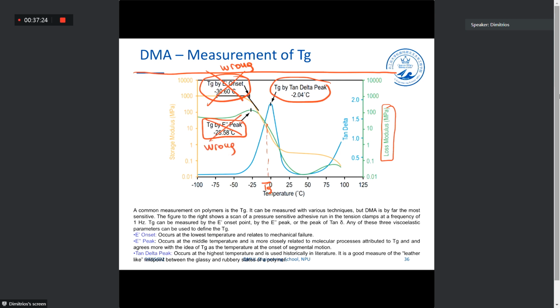And you can see how big a difference there is between the peak of the tan delta or the middle of the storage modulus versus temperature graph, where it shows a big downshift, a big slope. In this case, we have a -2 Celsius degrees glass transition, while the other two methods give us a glass transition of -30, which is wrong. -28 and -30. So anytime someone asks you to identify glass transition from a storage modulus or the tan delta or a DMA measurement in general, you use these two parameters that we discussed. Either the middle of this downshift, this yellow line, sorry, or the peak of the tan delta.